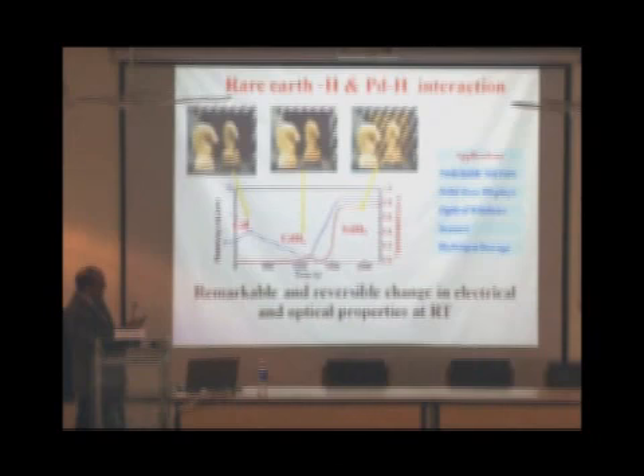And this is how you can see that when we put hydrogen, there is a large change in the optical properties, resistivity and transmission. Here it is metallic, transmission is very low, and here the transmission is very high. So this change in the optical transmission from this point to this point, or change in the electrical properties from this point to this point, is what is used in a large number of applications. One of them which we studied is the switchable mirror.